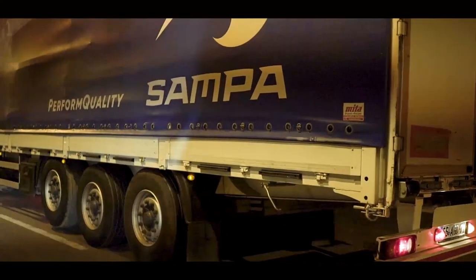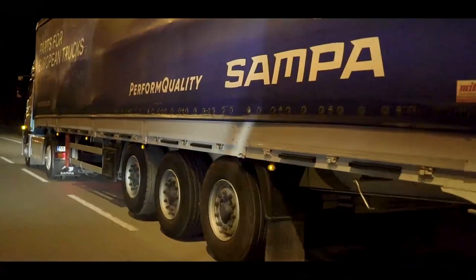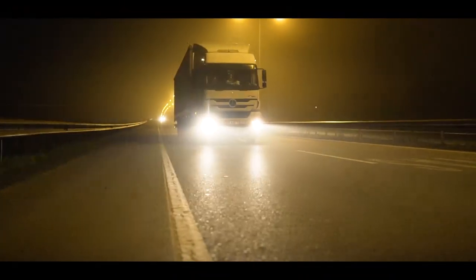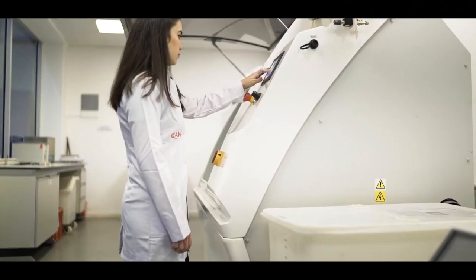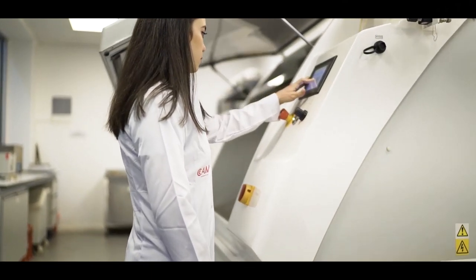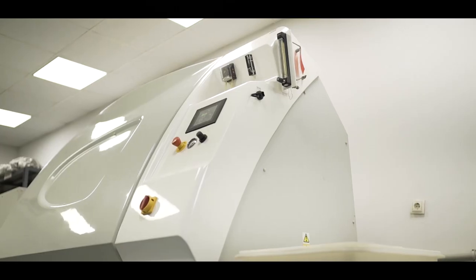Air springs must be resistant to harsh road and weather conditions. In addition to rubber, the desired durability of the metal components prolongs the life of the air springs. We have two salt testing devices in our laboratory. One is the salt spray testing device, and the other is the cyclic corrosion testing chamber. In our salt testing device, we prepare a 5% salt solution and spray the salt water on the part.